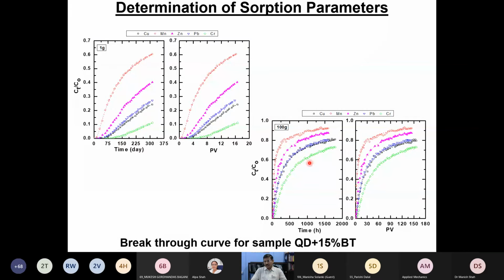The moment we conduct the same test in a 1g, after 1 year, I reached only 16 pore volumes of water coming out of the system. But in the case of a centrifuge, I got around 150 pore volumes. As a result, all my breakthrough curves are much above 0.5, which is good enough for me to calculate this.